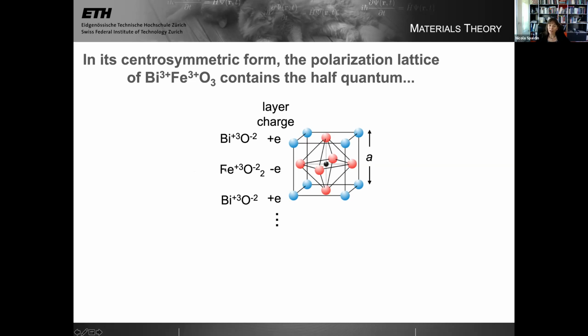So if I look at the layer charges per unit cell, I have exactly the same situation as in that simple cartoon we did earlier. I have plus 1, minus 1, plus 1, minus 1, equally spaced. And we saw already that such a structure has a polarization that doesn't contain zero.